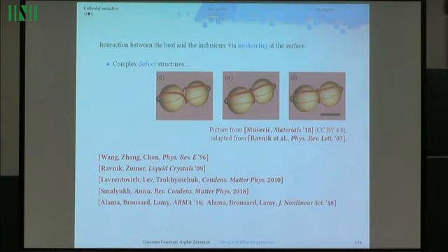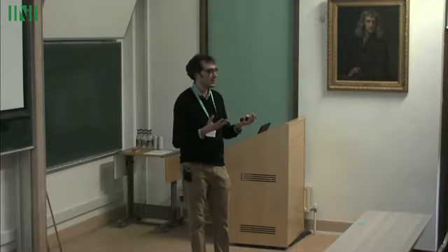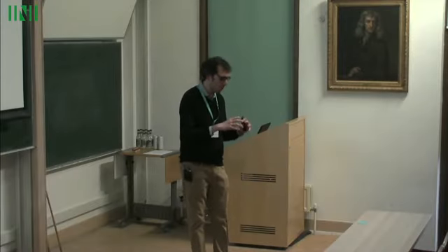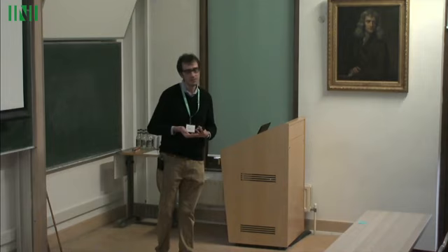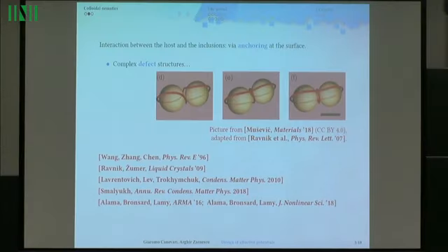Still, the presence of inclusions modifies the behavior of the material, and that's because even though there aren't dipoles, the inclusions still have a boundary. They have a surface. There will be an interaction between the particle and the liquid crystal molecules, an interaction that takes place around the surface. In fact, you may even treat the surface of your particles so as to induce preferred directions of molecular alignment. For instance, the molecules may prefer to stay aligned tangentially to the surface of the particle, or perhaps in the normal direction. And this anchoring, of course, modifies the arrangement of the liquid crystal molecules.